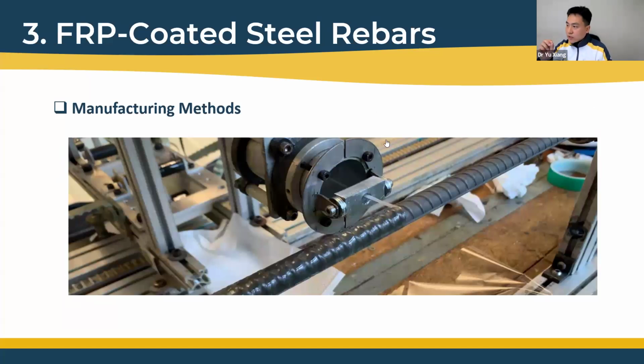We think we have 2 points to control the bubbles. The first is to control the tension of the fiber - we designed the tension to keep close contact between the fiber and the core steel rebar, so the bubbles will be first eliminated or reduced. Second, we have other procedures to control the air bubble, for example, we use vacuum pressure to make them more closely contacted together. So I think this is about this question.